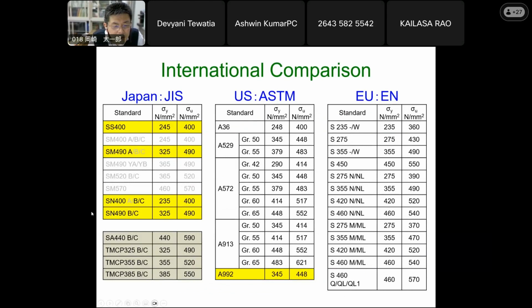Now, if you weld high-strength steel, there is a higher grade than this. The highest grade has a yield strength of something like 600 Newton per millimeter square. But if you go that high, it's impossible to find a weld electrode that matches that grade. So in that case, the current guideline is to make just a very big fillet weld. Okay, that's one thing I can say.